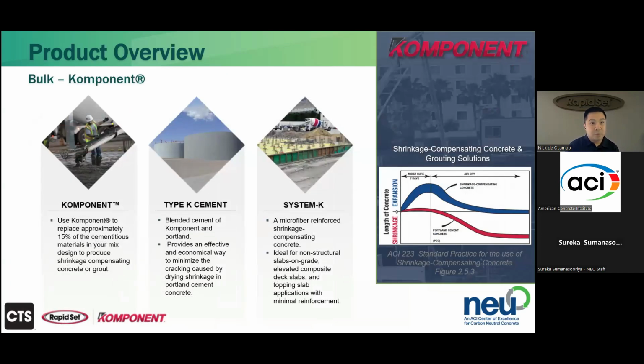I'm going to switch back to bulk and back to really the beginning in terms of Komponent and the shrinkage compensating material. Komponent is the extension of what Chemcomp was discovered to do. It's typically blended with Portland cement. It expands for the first 7 days, wet cured, as is demonstrated on the chart on the right there, that blue thick curve, where it's meant to expand for the first 7 days, and then the wet cure is removed. It starts to dry cure, and based on the expected shrinkage of the Portland cement, is supposed to come down to basically dimensionally stable as 0 expansion, 0 shrinkage material.